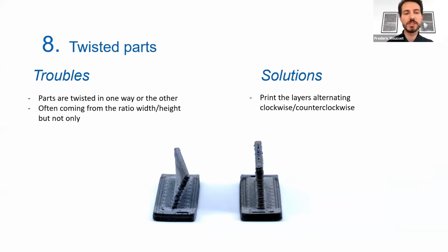So yes, for this part, I'm going to insist on the fact that often when this happens, the ratio of the width and height is quite different, and this is why it twisted a bit or a lot depending on the piece. But sometimes it isn't the width to height ratio. It is very rare, but if it is happening, we have a perfect solution that is working every time, and this is to print the layers alternating clockwise and counterclockwise.